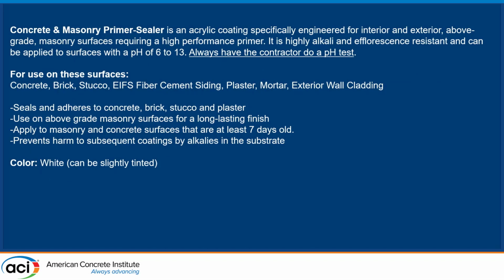Concrete masonry. You might see concrete primer, masonry primer, sealer. Like Mark talked about, a lot of the tilt walls have high pH. You want to lower that. There's some, like I said, primers that will accept pH of 6 to 13, so it allows you to prime that tilt wall quicker, allow that contractor to top coat it.